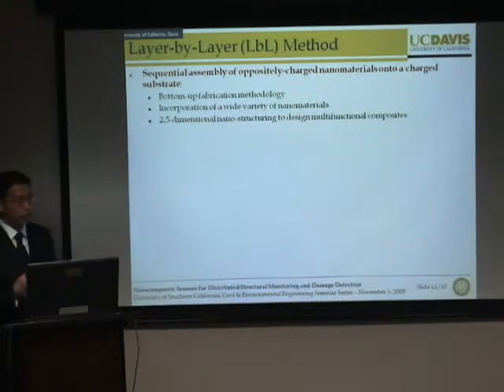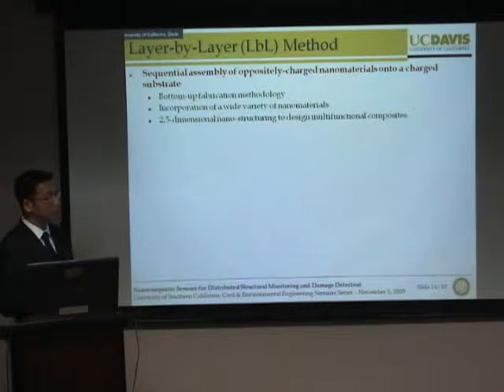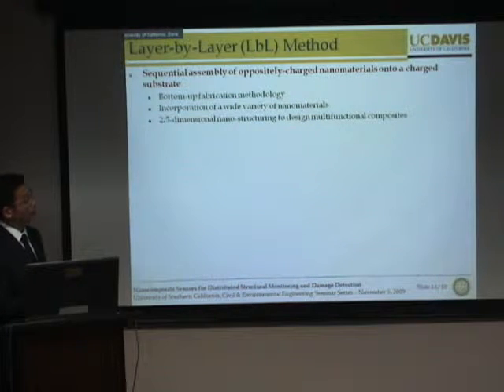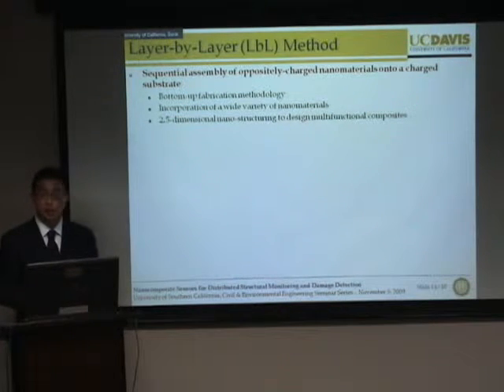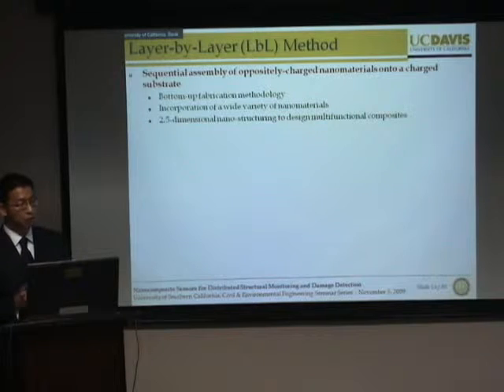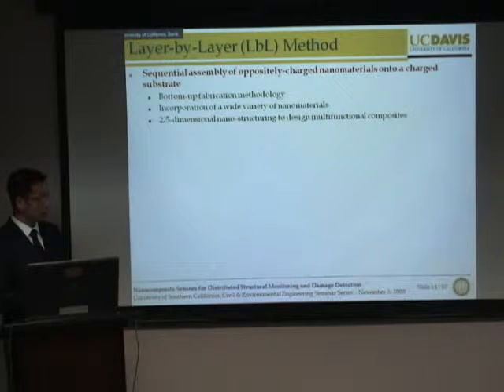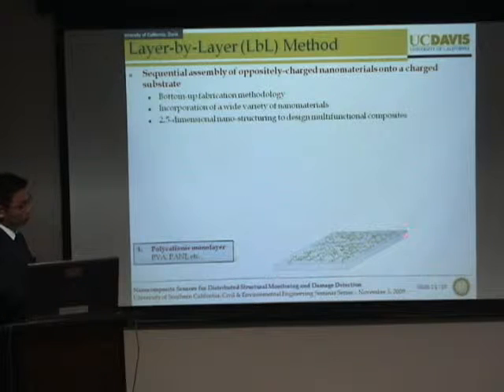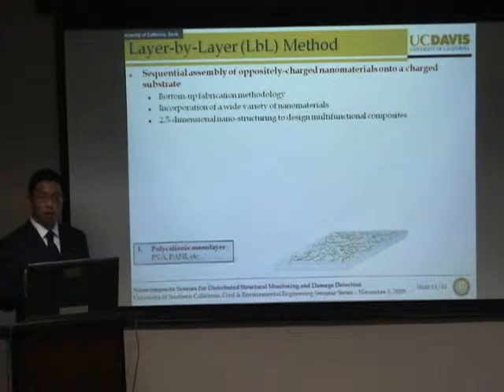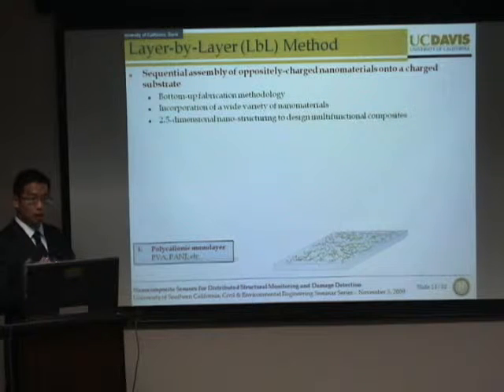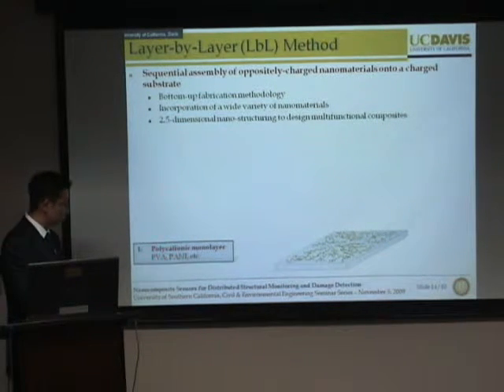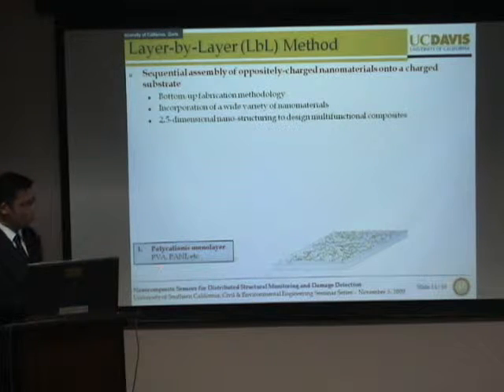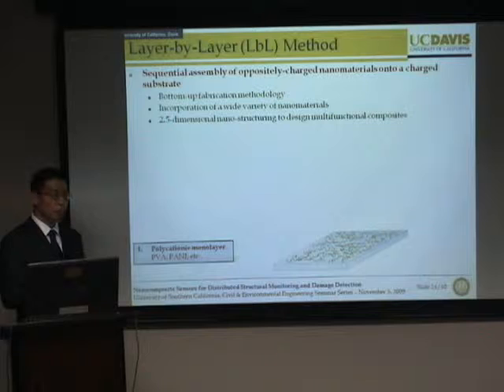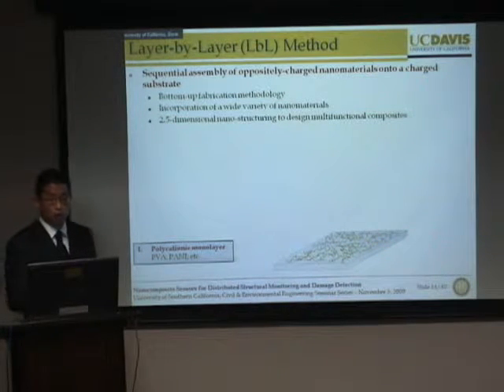So for our study, in order to enhance our control to manipulate these materials, we've taken advantage of a thin film fabrication technique known as the layer-by-layer self-assembly or template-assisted method. Essentially, the layer-by-layer method entails the sequential deposition of oppositely charged nanomaterials onto a charged substrate. To better visualize this process, we take a charged substrate, such as glass, silicon, or different types of polymers, and immerse it into a positively charged polyelectrolyte solution, such as polyvinyl alcohol, PVA, or polyaniline, PANI. Over time, the positively charged molecules will adsorb onto the charged substrate.